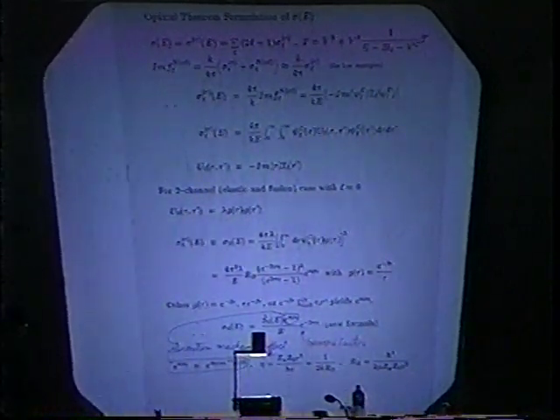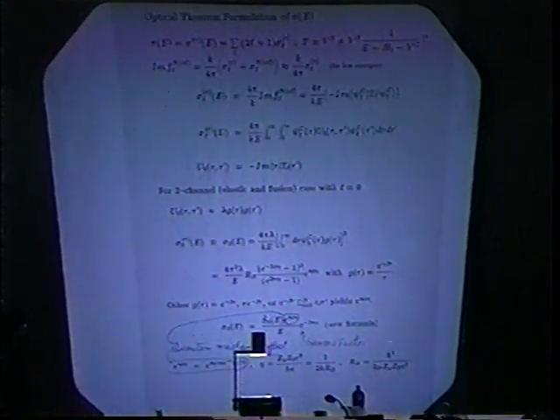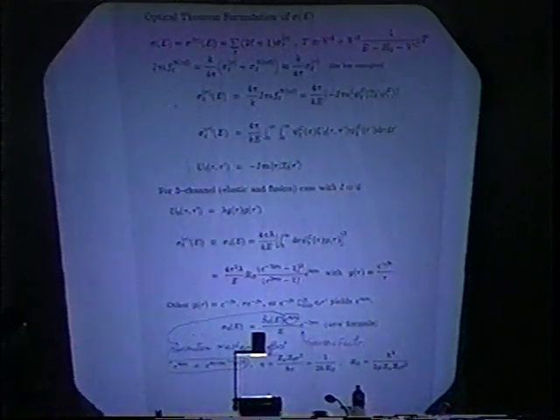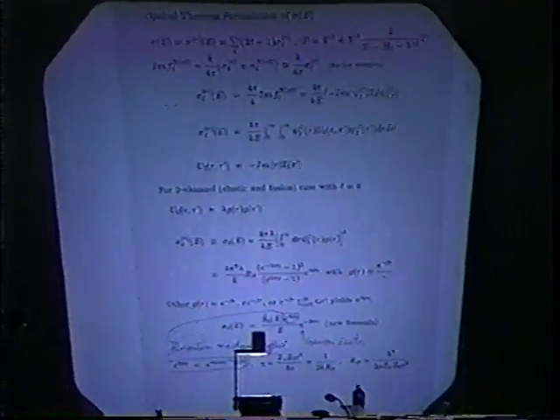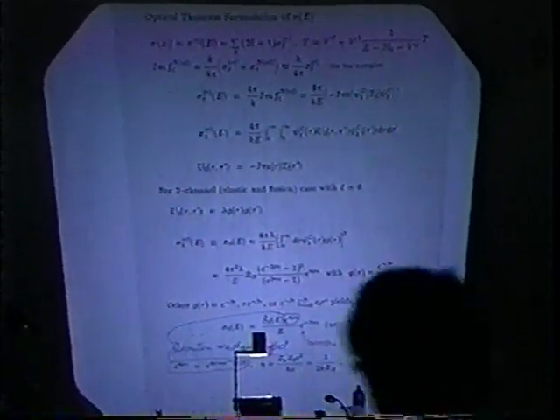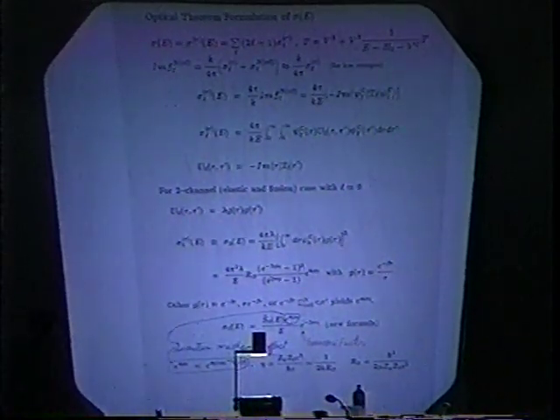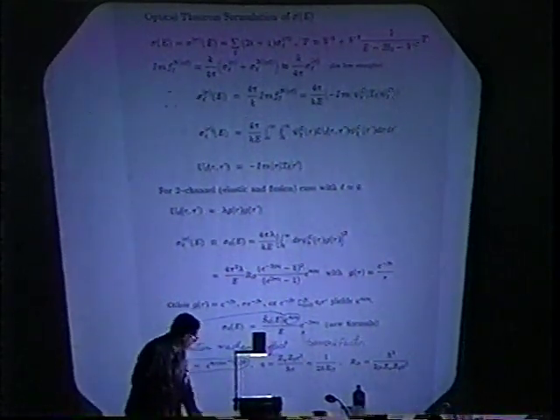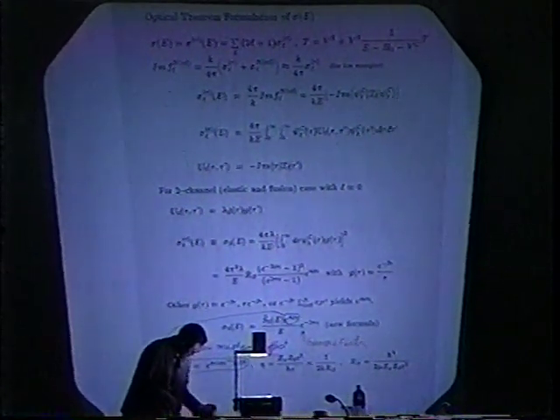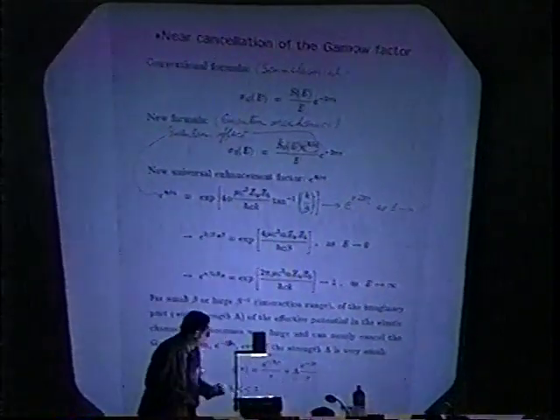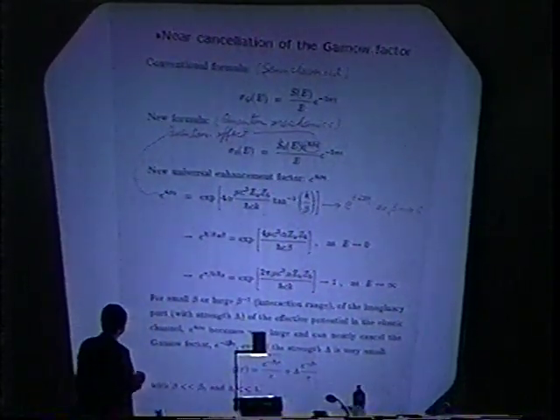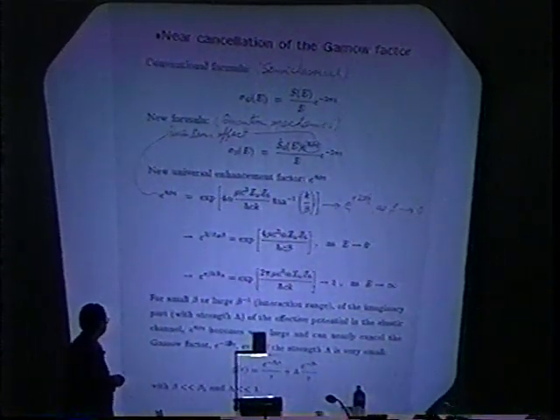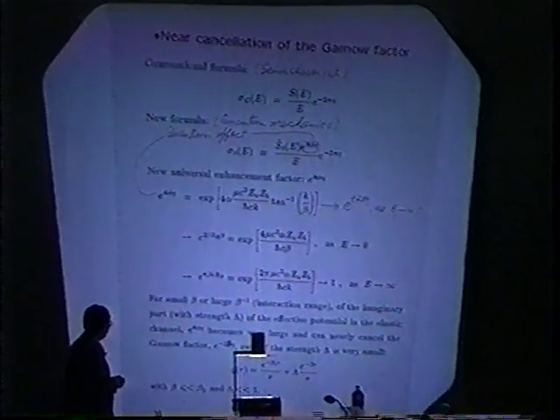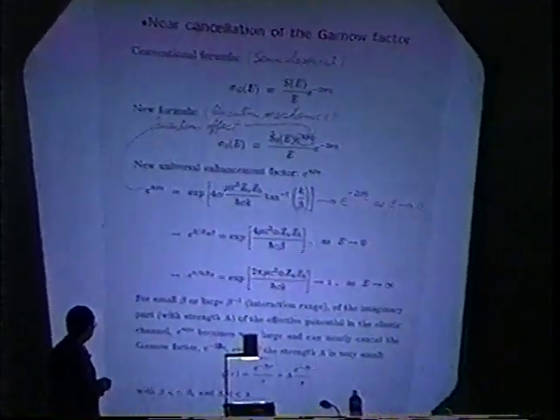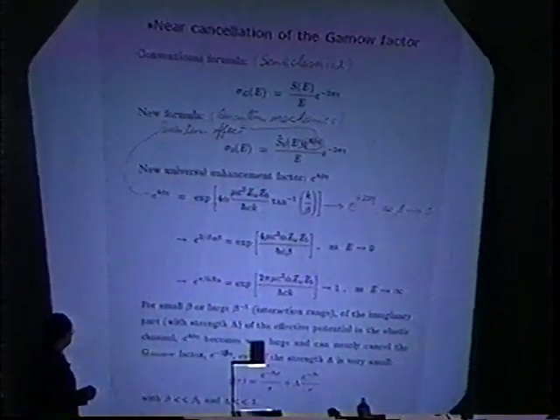Beta, inverse beta, will be the range of the interaction. Then you get this new formula. Now we change this form to this form, and to more complicated forms, yet we end up with this common factor. So we are very comfortable that this is indeed a feature of the quantum mechanical derivation. So let's look at that term and what it can do for us to stay in the business. It has this structure, and if you make the interaction range, inverse of beta, large, or beta small, it can be exactly the same form but with opposite sign to the Gamow factor.